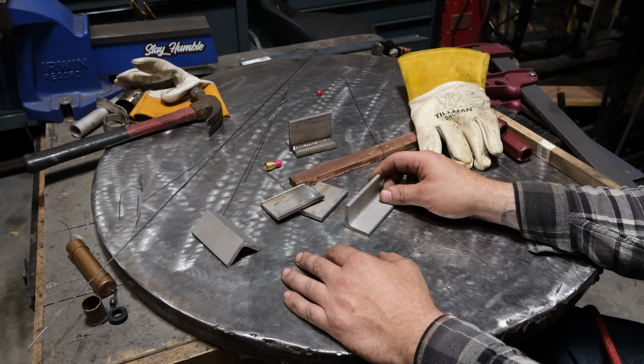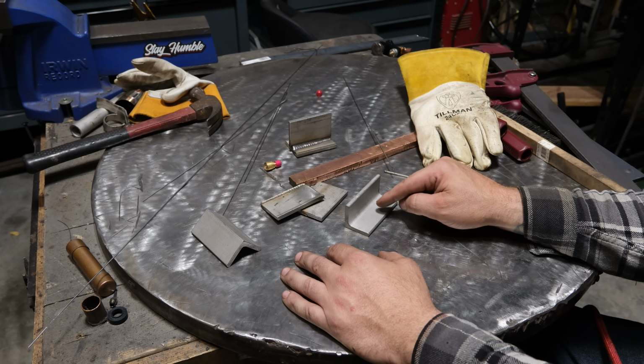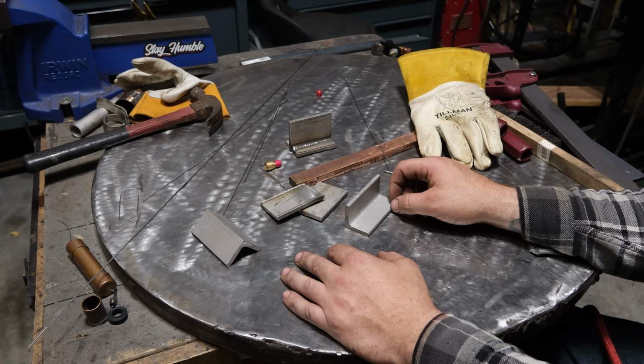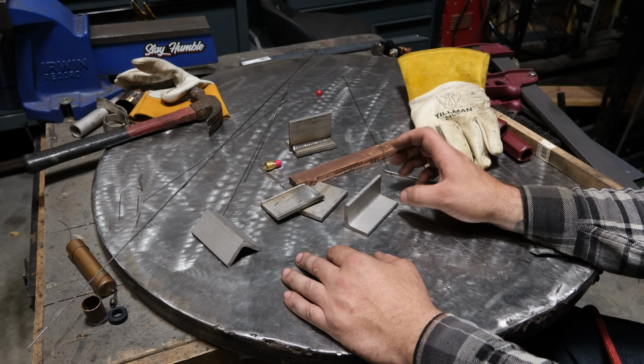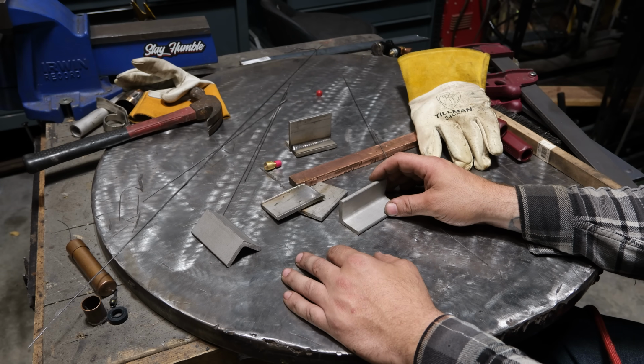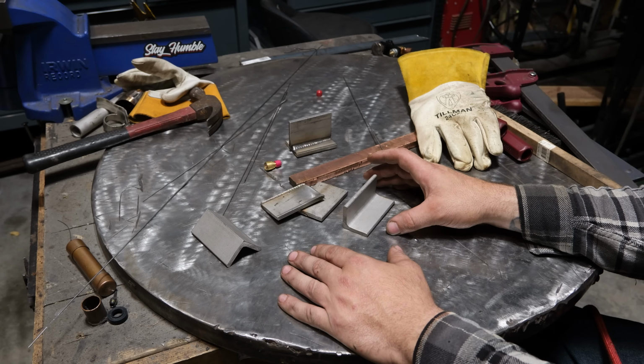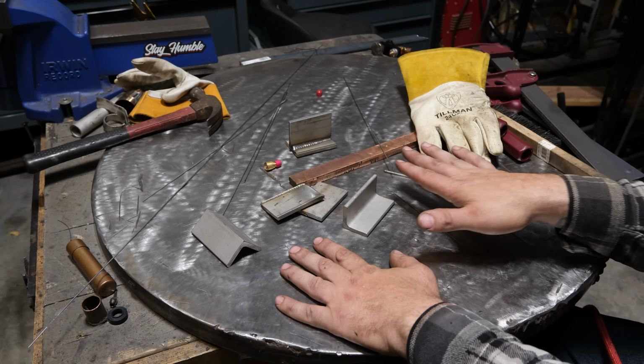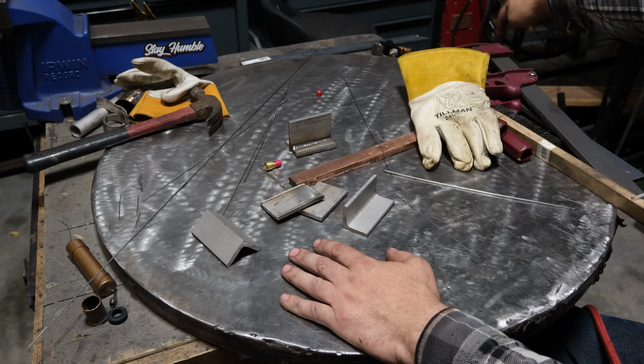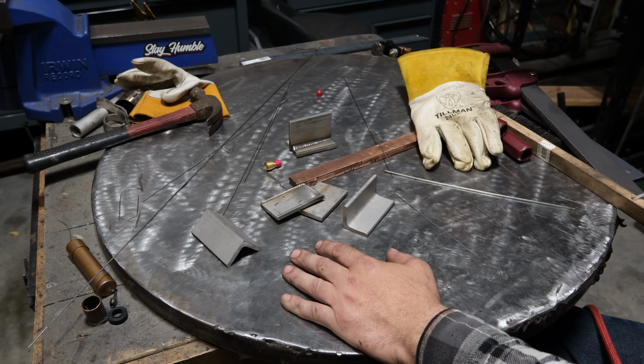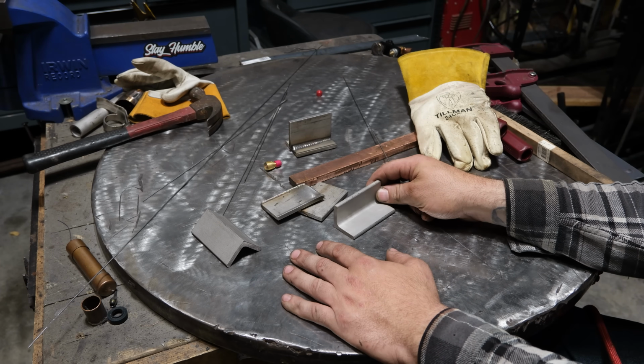This stuff, if you have a poor ground, will drive you absolutely bonkers because the piece will start vibrating. You can get weird arc wandering where the arc will wander to one piece and not the other. So it's always in your best interest working with stainless to have really good conductivity to your ground clamp. Now, in the case of this table, I have my ground clamp on this copper cable down there, and even I was getting wobbling.